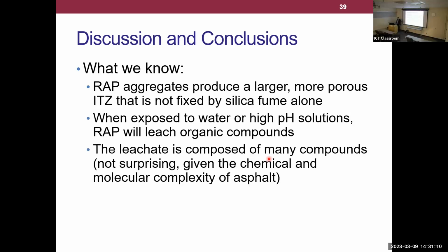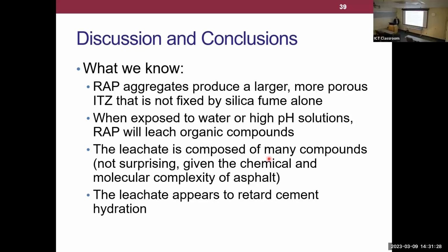Again, there's a bunch of compounds. We saw that with a bunch of different techniques. We were not able to identify what specific compounds were present, because there's probably just a lot of them. That shouldn't be a surprise when we know asphalt itself is fairly complex. And then we also showed that there appears to be a retardation of cement hydration. We're somehow delaying or negatively impacting cement hydration because of this leachate. We have not proved if it is some sort of mechanism that's stealing calcium like we initially thought. That's something we still have to prove.